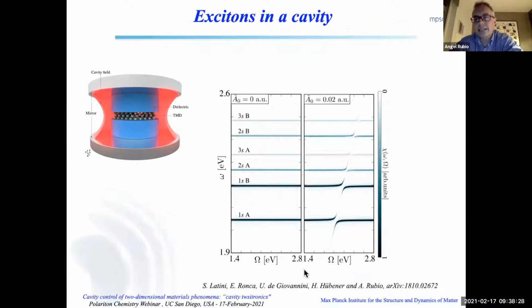Basically, you will get the photon dispersion, which is linear. And then what you get is exactly what you would expect. As when the photon dispersion hits one of the dipole allowed excitations, you get the formation of the upper and lower polaritons, and this goes up all the way. Then for the weak coupling regime, you get what you would expect, and it is in the perturbative regime.